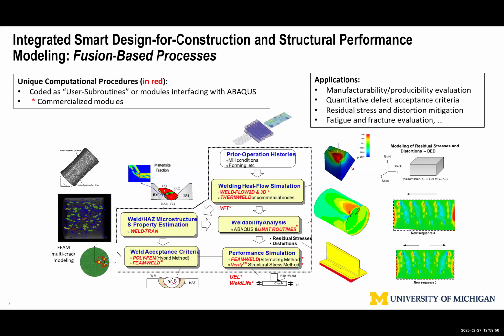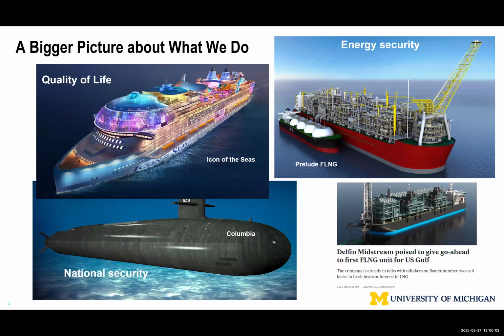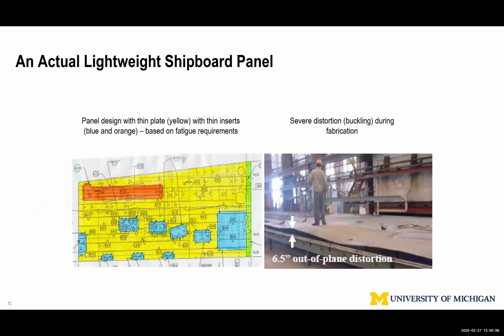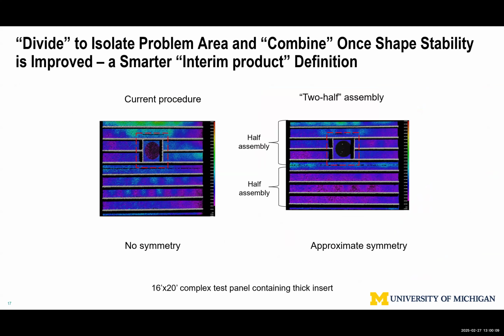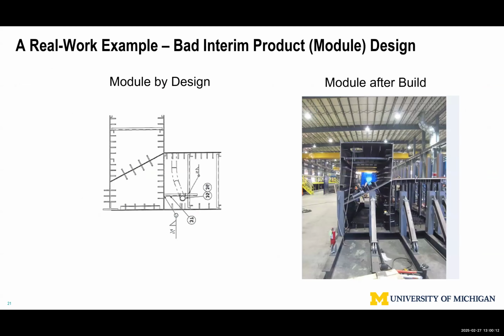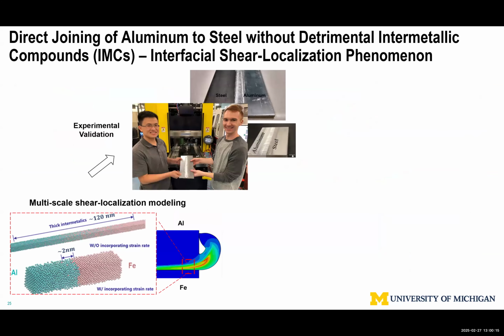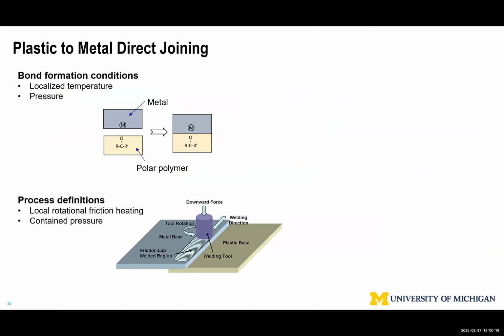So my question was simple. I was wondering in the lab, how did you actually achieve that? Very simple. I think that's in the one chart I just went by pretty quickly. It is in our lab, but we could go to the machine disassembly. We just use a CNC machine essentially. This is just cylindrical tooling, H13. It's very cheap. Because if you deal with aluminum, you don't need a special alloy. You put this in a tool holder, rotating and sliding. It can go to 5 meters per minute, pretty fast. But that already satisfied our automotive requirement.